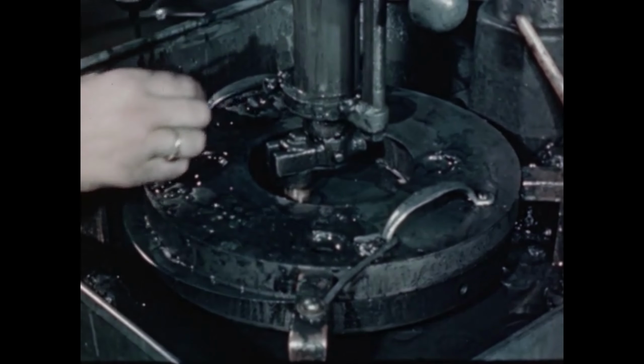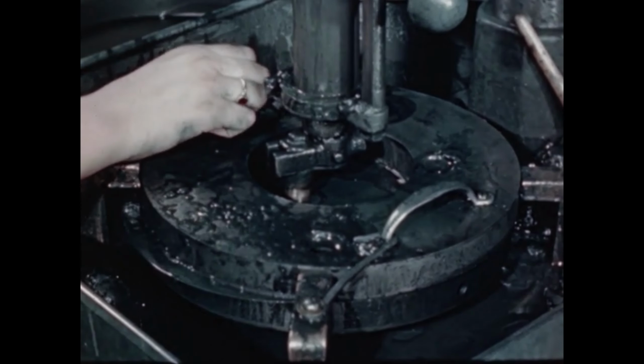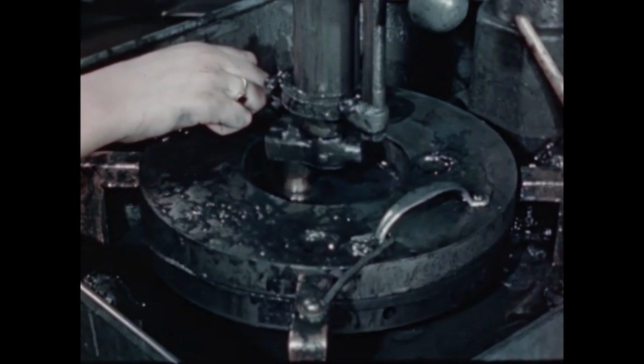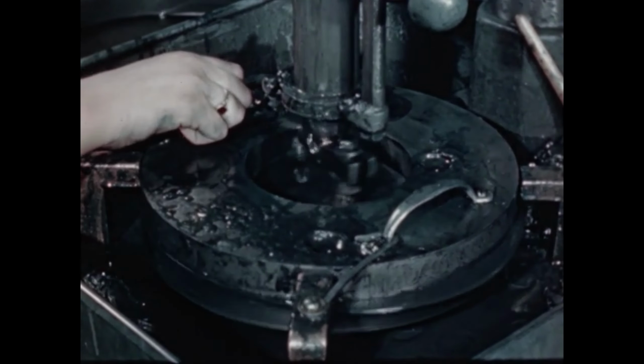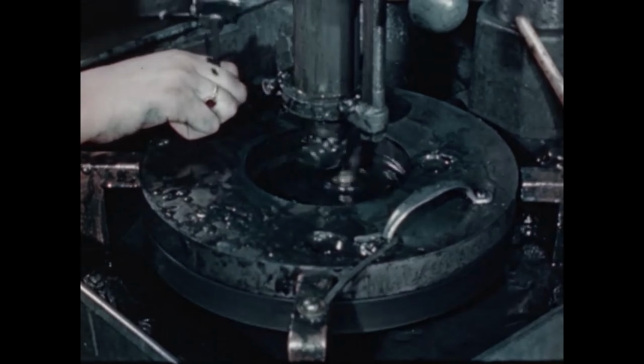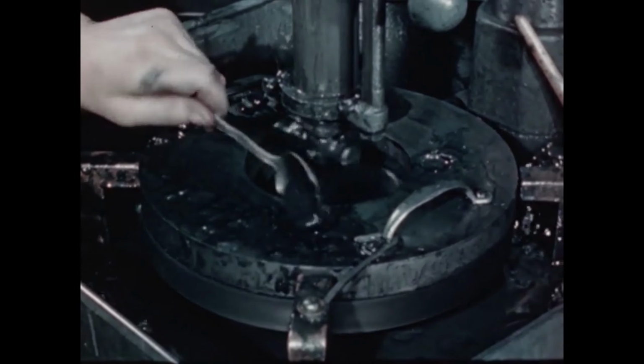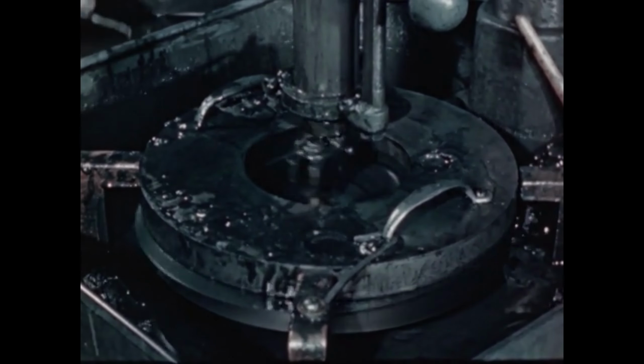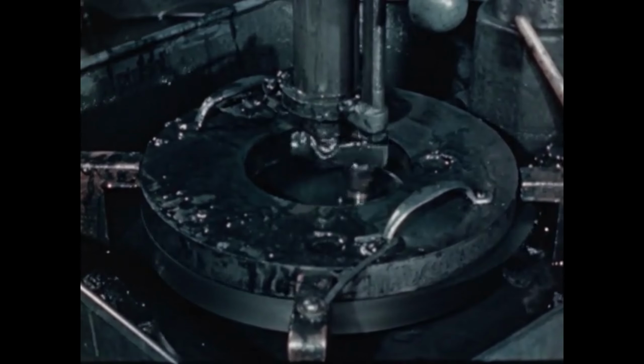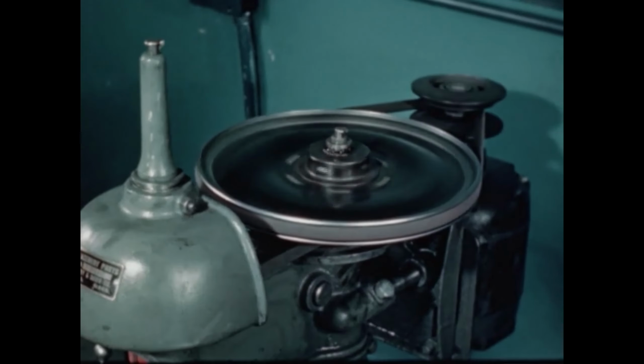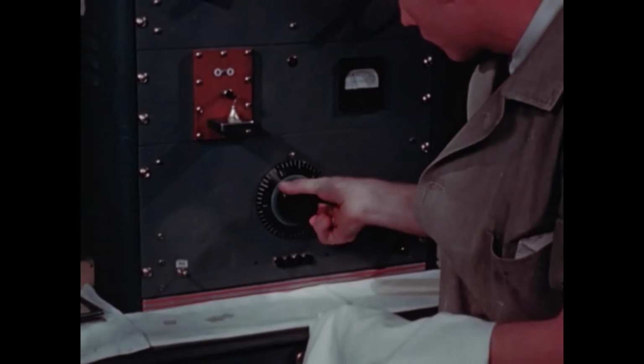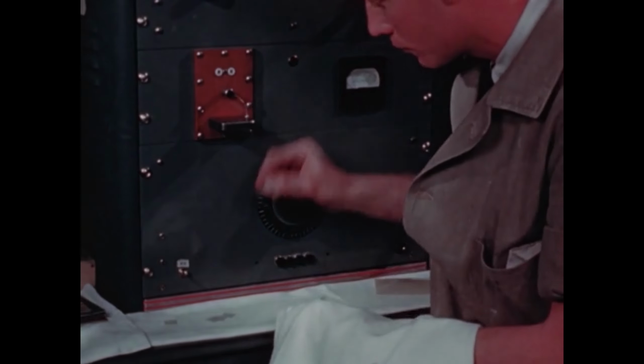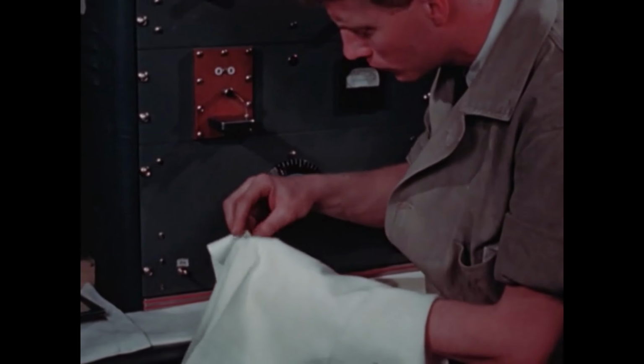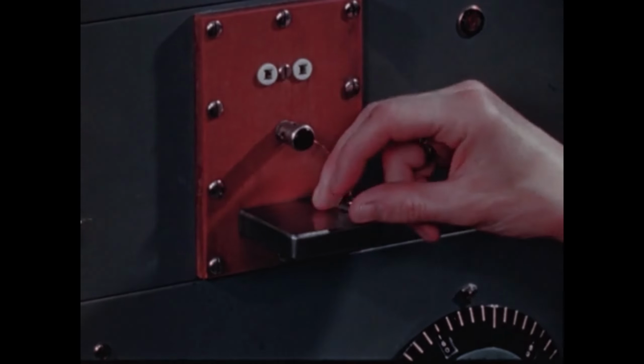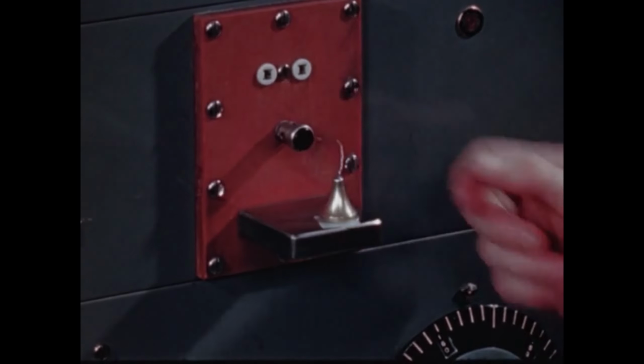To hit the exact radio frequency required for wartime comms, these quartz plates had to be ground down to a terrifying tolerance, a millionth of an inch. Lapping is done with a comparatively coarse silicon carbide abrasive. Upon adjustment of the dial, the meter tells the activity of the blank, and at the same time, an audible tone indicates the frequency by comparison with the standard.